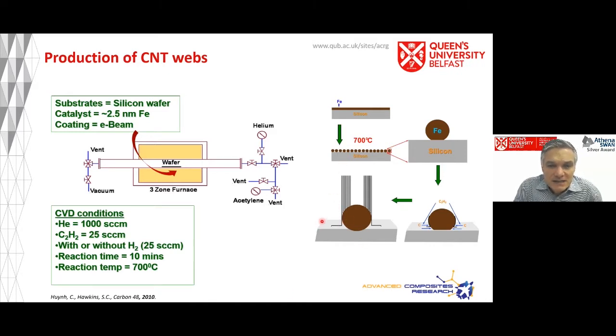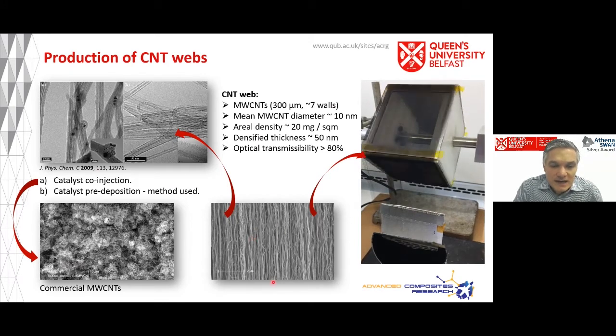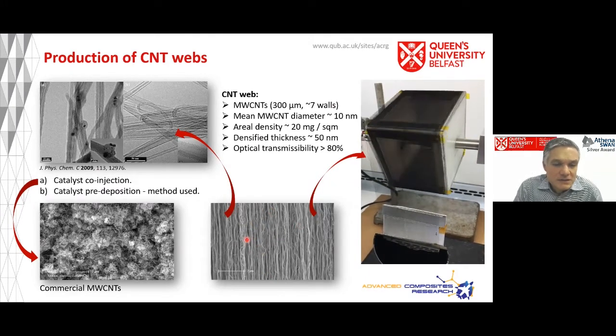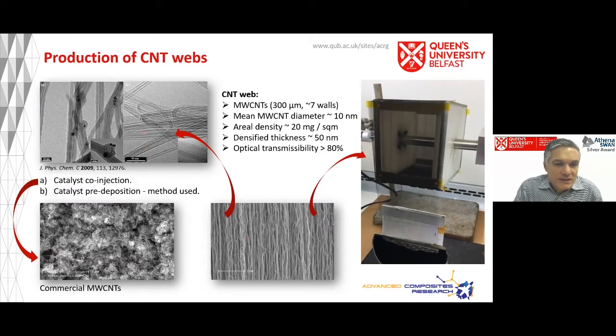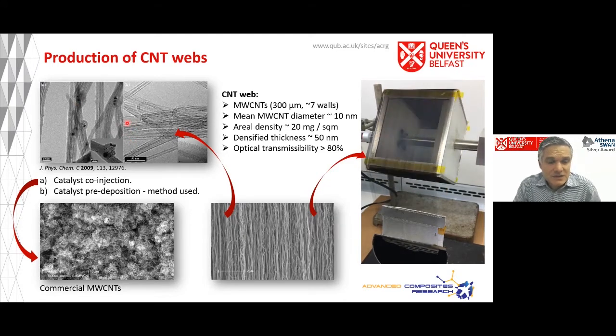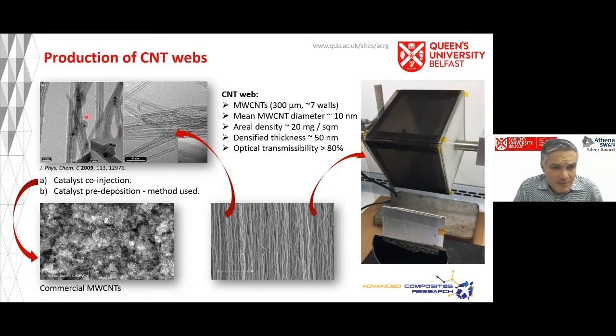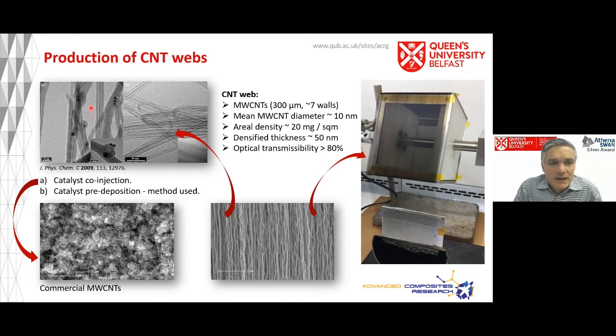And what's interesting is that the carbon nanotubes actually grow from below. The carbon is drawn in onto the catalyst, and then the carbon nanotube extends upwards. Now, what's nice about this is that the carbon nanotubes are very clean. There's no catalyst. There are other methods of producing these. You can do this with what's known as a catalyst co-injection method, where what you end up with is a randomly highly entangled mix of carbon nanotubes and catalyst. But of course, our catalyst remains on the silicon, and what you've got is this nice forest.